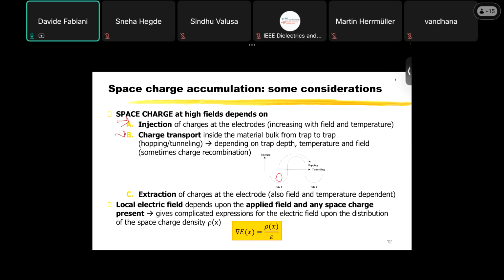This negative charge can hop or tunnel from one trap to another. But this takes time, of course, and depends a lot on the trap depth. So the deeper the trap, the slower is the transfer of one charge from one trap to another one. And if the charge remains for a longer time in a trap inside the insulating material, then of course it can distort the electric field.